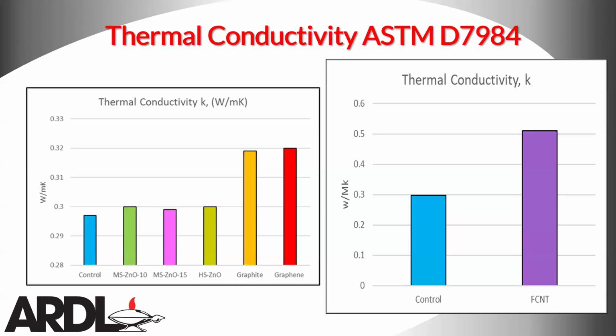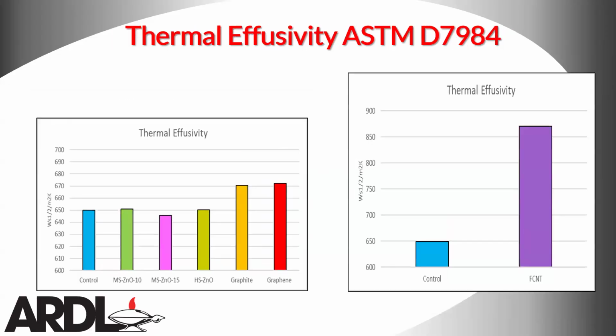So I'm still getting high thermal conductivity, and I'm still getting good heat resistance because it's there. But the reason why it's not helping the abrasion resistance, like I said, is because I think it just doesn't have a lot of affinity for the polymer because it's not treated. So if I look at my functionalized carbon nanotube, you can see that I have much higher thermal conductivity than all of the other fillers.